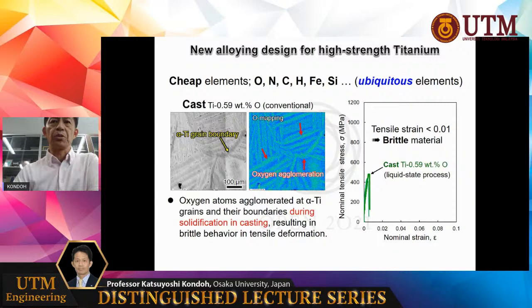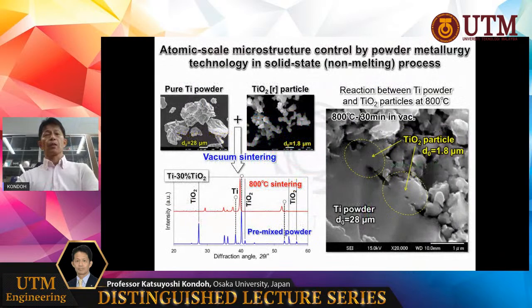So based on these results, we use powder metallurgy technology in solid state, non-melting. That is quite different from the conventional casting process. The powder metallurgy process is very simple. For example, shown here, titanium powder is the matrix material, and TiO2 rutile particles are the original source for oxygen additions.